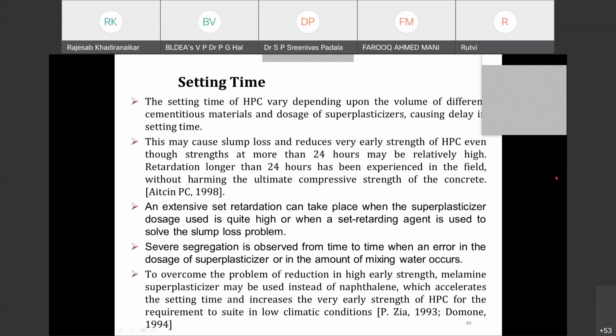Severe segregation is observed from time to time when an error occurs in the dosage of superplasticizer or in the amount of mixing water. We have to be very precise while adding the constituent materials. To overcome the problem of reduction in high early strength, melamine superplasticizer may be used instead of naphthalene. Of course, this is literature related to an earlier period. Now most of us are neither using naphthalene nor melamine. We are going in for the fourth generation. But if you have a choice between SNF and SMF, this will help you.